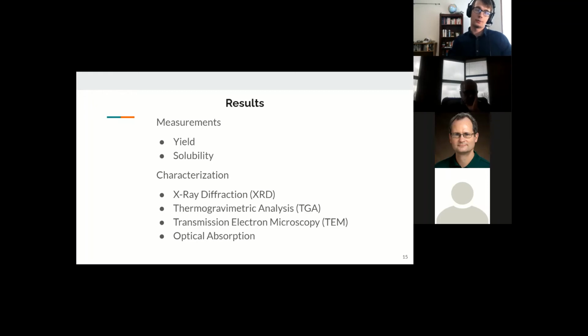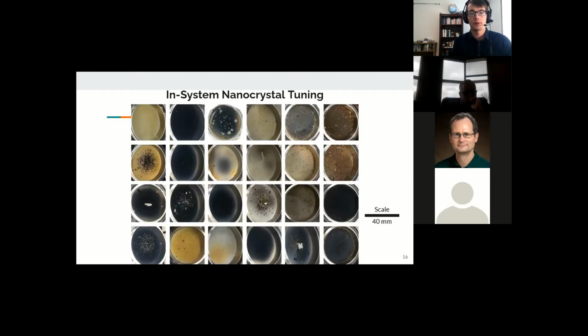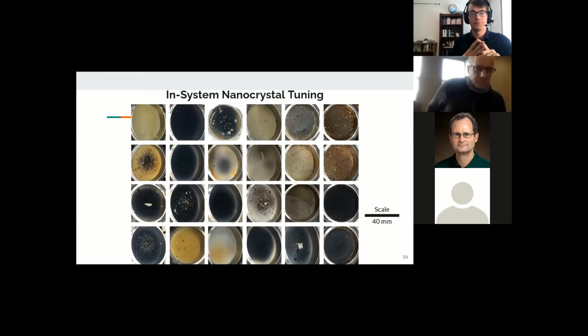The characterizations performed on the powder were X-ray diffraction, abbreviated as XRD, thermogravimetric analysis, abbreviated as TGA, transmission electron microscopy, abbreviated as TEM, and optical absorption measurements. As well, we measured the solubility and the yield of the powder. The system can be tuned in many different parameters. For the studies presented in this thesis, the tuning parameters chosen to vary were the reactor pressure, the reaction gas flow rates, and the carrier gas flow rate.